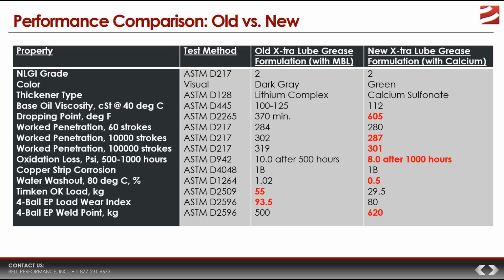But remember, people aren't choosing whether to buy the new X-tra Lube Grease or the old one. They're having to make a choice between the new X-tra Lube Grease and another kind of grease that's currently being sold. And even though we don't have it up on the screen, a typical lithium complex grease is going to have a load wear index somewhere in the 40s, maybe 50, not much above that. So the new X-tra Lube Grease really blows away those kinds of greases when it comes to load wear index, because it has a load wear index of 80.